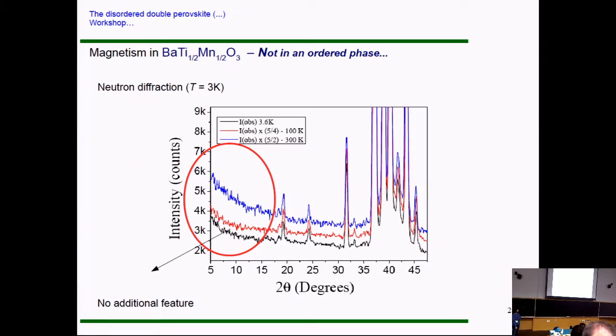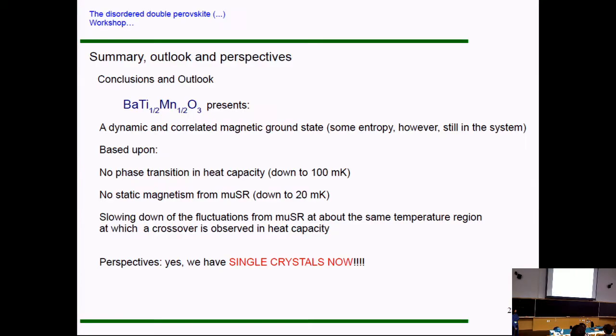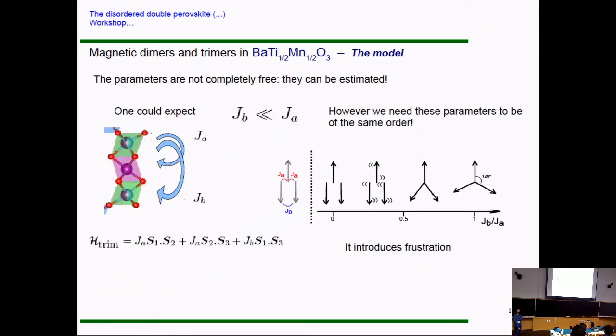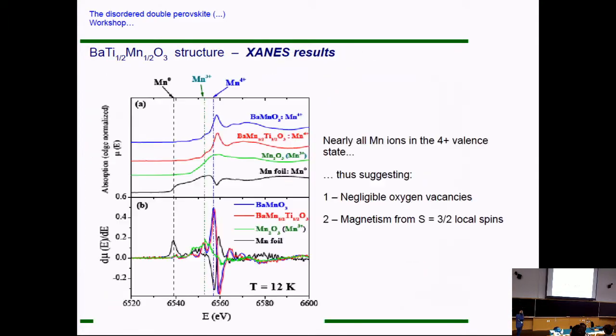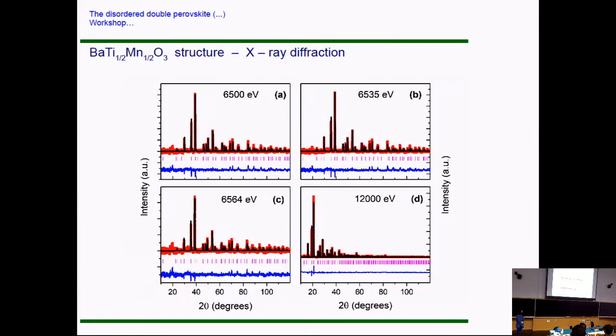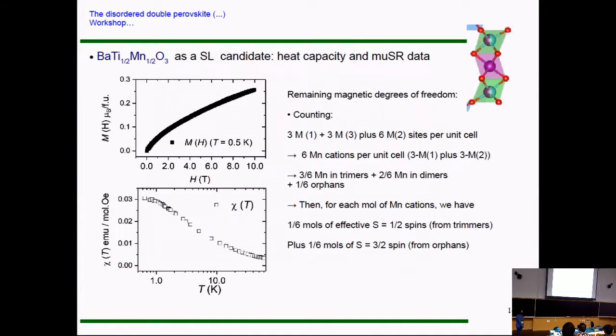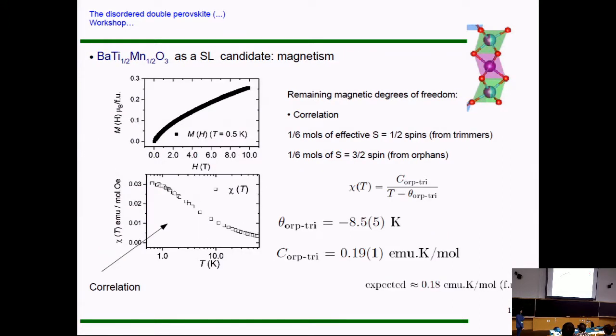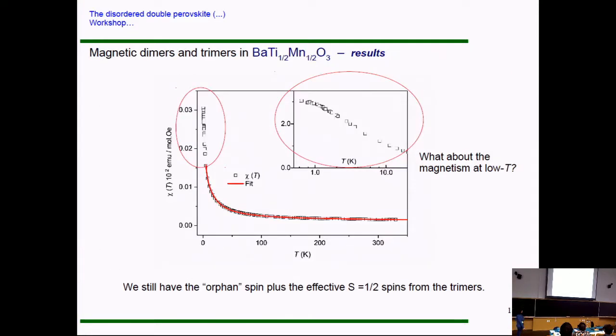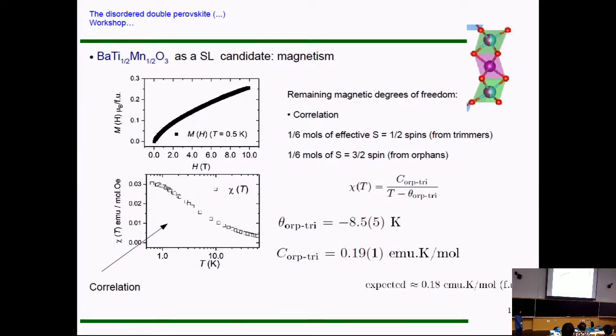Yeah, the scale that we extract is something, okay, so what we can say is that these remaining degrees of freedom are correlated, and the energy scale is about 8.5 Kelvin. That's all I can say. And if I compare that with the lowest temperature that I can measure in heat capacity, I can safely say that I have a frustration factor of about 80. I cannot say that my frustration factor is due to the high-temperature Curie-Weiss constant that I got. It's not that. I must compare with this number here. But it still gives me a pretty high frustration factor for the system.